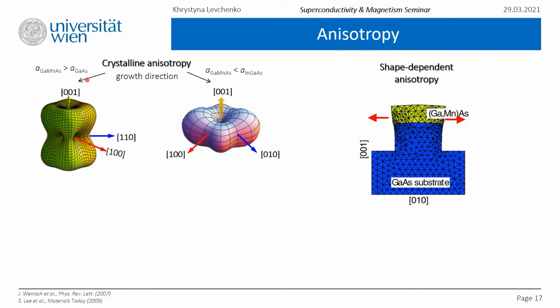In the case of gallium arsenide, we have a biaxial compressive strain, as was mentioned earlier. It means, as is brilliantly illustrated in these pictures, these magnetostatic free energy surfaces derived from the magneto-transport measurements under different applied magnetic fields at low temperatures. So in this case, we have two easy directions. The first one is the original [100], which is a cubic anisotropy, and the second one being [110]. Usually the situation for the compressively strained films is even a bit more complicated.